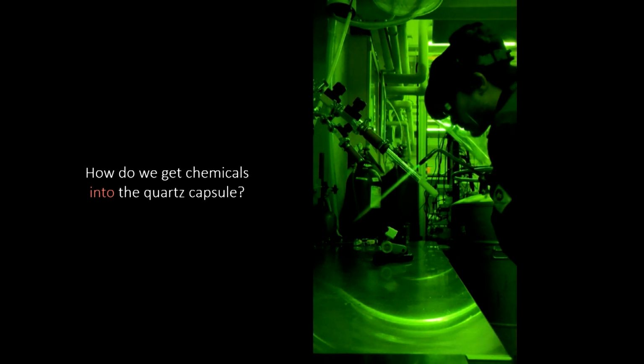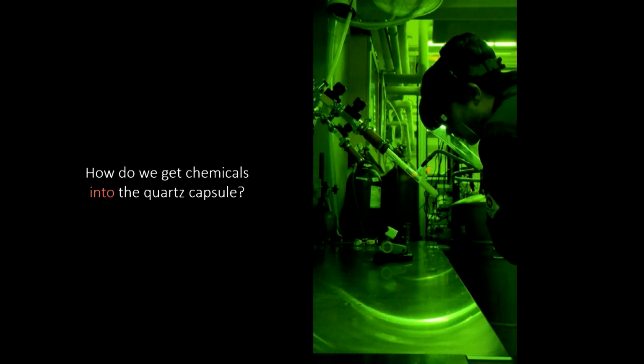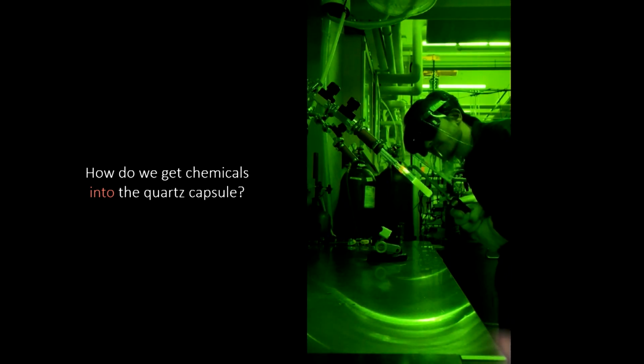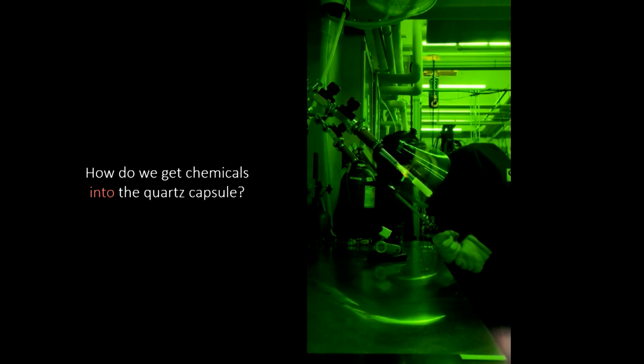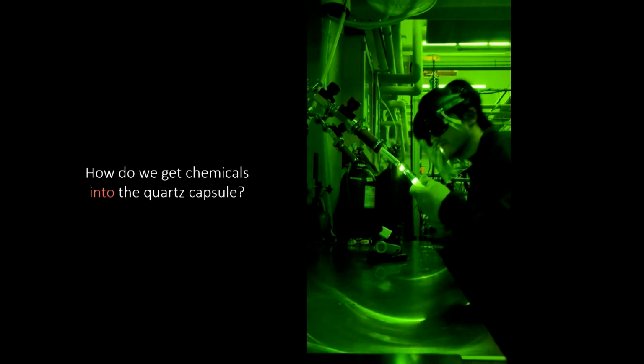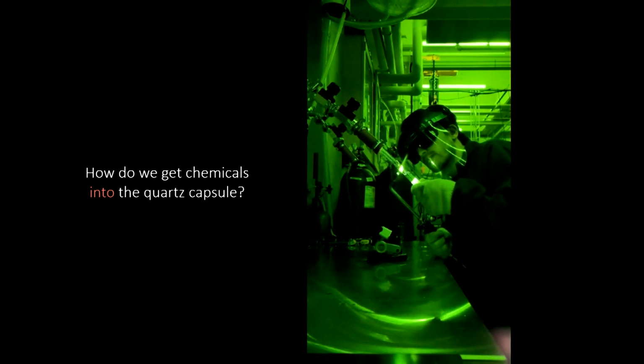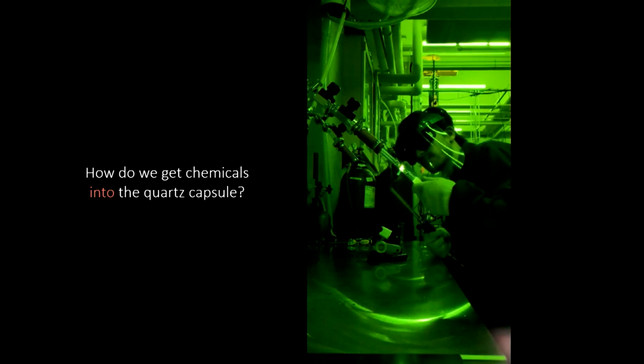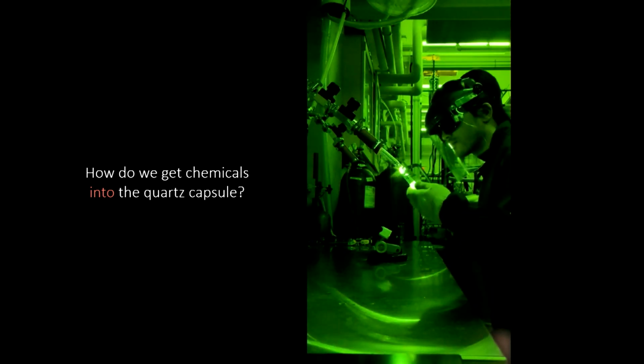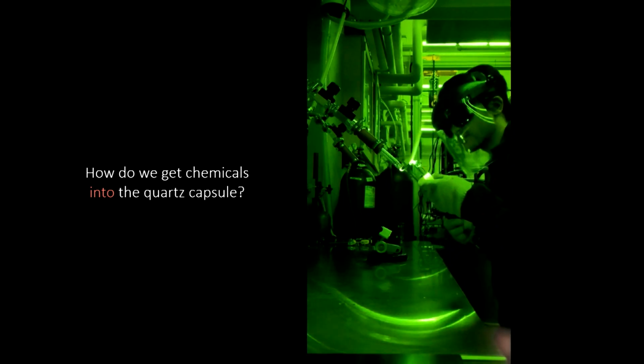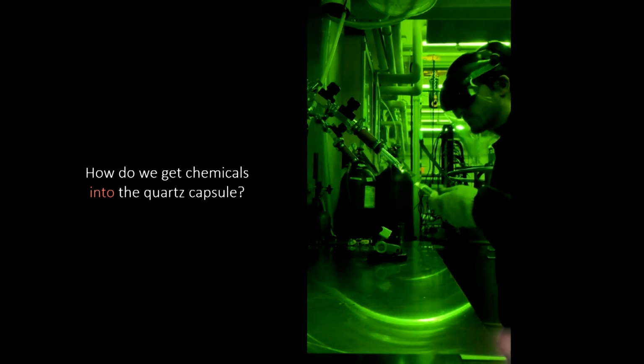So this is a day in the life of an experimentalist. I'm using an oxyhydrogen torch with some safety gear: fireproof gloves and coat, and a face mask and goggles not unlike the ones you use for solar eclipse observing. We're burning tanks of oxygen and hydrogen at thousands of degrees Celsius, and I'm necking the tube. I'm collapsing it while I'm pumping out all of the air from the system. All my chemicals are in my hand, and I'm trying to homogeneously collapse it in on itself until it gets all molten so I can just pull off the connection. It's a really awesome way to do this. It takes a lot of practice, a lot of finesse, but once you break a bunch of tubes, you can get really good at this, and it feels very good.